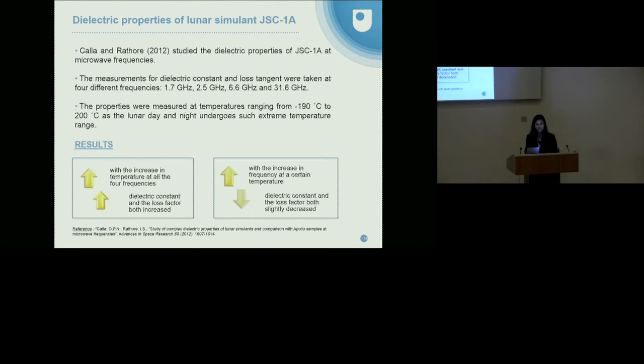They tried to do the tests at temperatures ranging from minus 190 degrees Celsius to 200 degrees Celsius, as the lunar day and night undergo such extreme temperature ranges. And they tried to establish the relation of dielectric properties with the temperature. The results were quite interesting. With the increase in temperature at all 4 frequencies, the dielectric constant and the loss factor both increased. But with the increase in frequency at a certain temperature, both the values decreased.